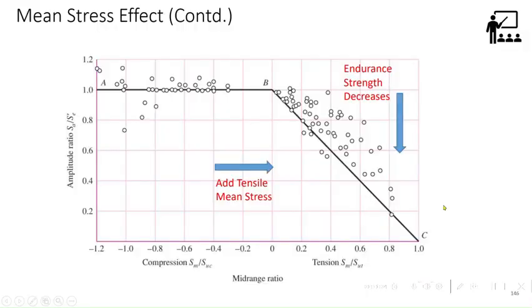But why are you considering only the positive side? Because it has been shown experimentally that anything below 0, that is, all negative mean stress, is insensitive. It doesn't affect your stress ratio. If you recall, one of the slides showed R positive going below, and R compression showing higher than R equal to -1, but in reality it doesn't make a difference. They fall side by side with R equal to -1.